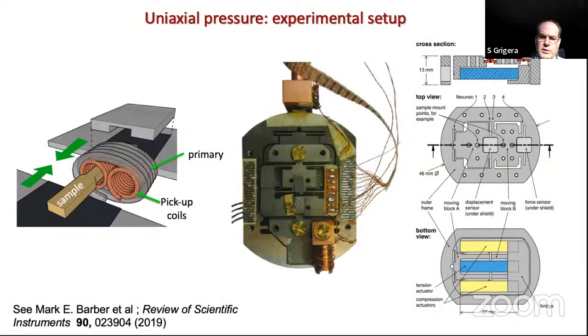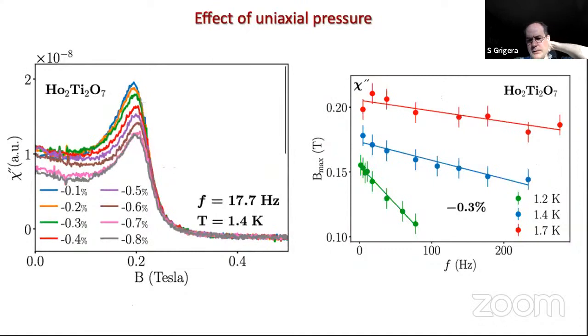So what we did was to use this type of experimental setup, where essentially what you're doing is putting your sample between these two piezoelectrics, and essentially use three piezoelectrics so that they compensate each other, and when you change the temperature, the system doesn't add or remove any tension. And this is what happens when you start putting uniaxial tension into the system, which, as you see here, is very little. So we went to -0.1 to -0.8%.